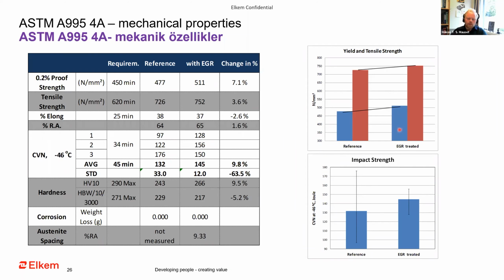And this one you see here in these figures as well, that there is an increase in both yield and tensile strength when EGR is added. And yeah, for these grades, the most important is of course the impact strength. So you can see here that the reference, this is the average, but there is a big spread between the values. Here we have an overall better average and much less spread.